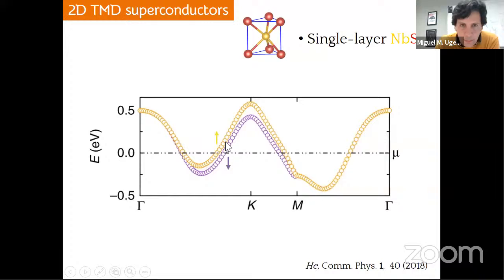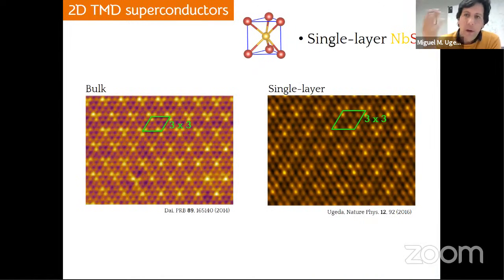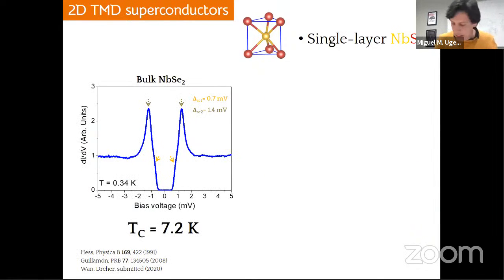So these are the spin-up subband and the spin-down subband. But other than that, the electronic structure is quite simple. So we know from previous measurements that the single-layer form of niobium diselenide retains the charge-density wave that was observed for bulk in a similar 3x3 configuration. So what you see here, apart from the atomic registry, is the 3x3 supermodulation that comes from the charge-density wave. And we believe that the critical temperature is quite similar with respect to that found in bulk, which is 7.2 Kelvin.